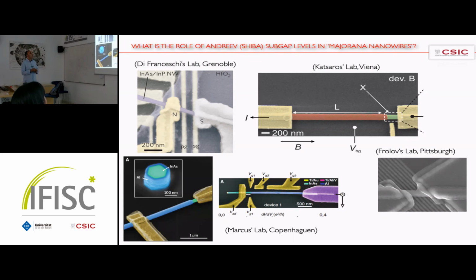And typically, in practice, what you do is you create some tunneling region here. The brown here is the part of the nanowire which is covered by the superconductor, while green is the part which is uncovered, because you want to gate this short region in order to create some tunneling barrier, okay? You want to do tunneling spectroscopy, transport. This image, for instance, is from Yorgos Katsaros in Vienna. This is another example, in Copenhagen. You see, again, the green and the blue.